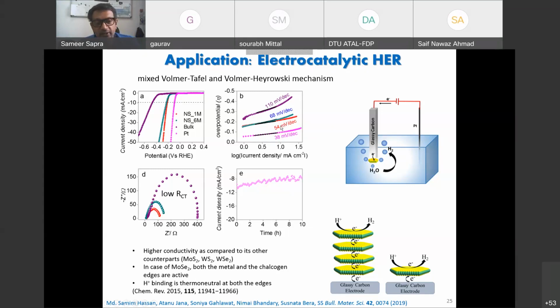Given the fact that MoSe2 is 60 to 70 times cheaper than platinum, I think one can settle for this. So these are very, very good results indeed with MoSe2. And the materials are very, very stable with time, right? And what it shows over here is exactly what I've told you, that it is more resistive for the charges to flow in multi-layers compared to 6 compared to 1 monolayer. These are nothing but impedance studies.